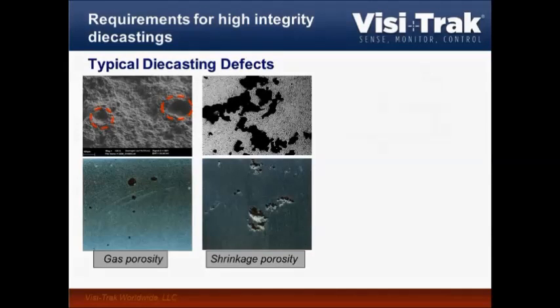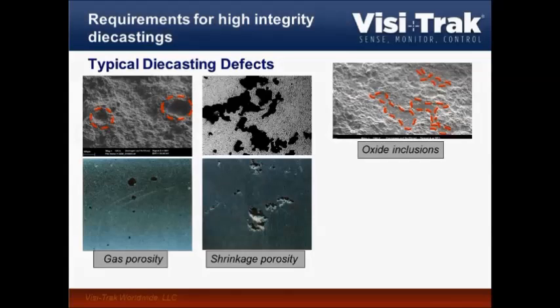Shrinkage porosity, we all know that. When we try to feed a thicker section through a thinner section, or anytime we have a thicker section, we risk that. Then of course oxide inclusions, which will often lead to shrinkage porosity because that's where the materials just don't bond together anymore. These oxide inclusions simply come whenever the oxide surface from the melt was folded over, and these folded oxide films got washed into our melt and then end up in the part.